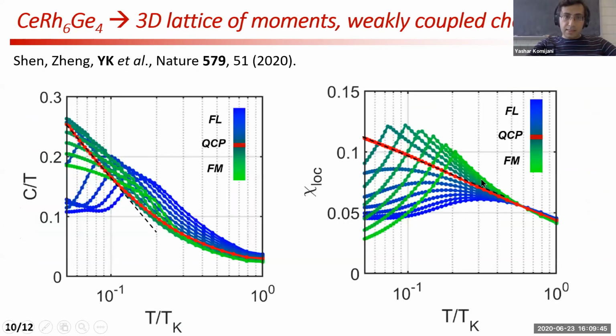All right, so we can try to use the Schwinger boson machinery to also model this system. We model it with a 3D lattice of moments, located on weakly coupled chains. And again, each moment has its own conduction path. And this model does a relatively good job in capturing the susceptibility. And you can see that